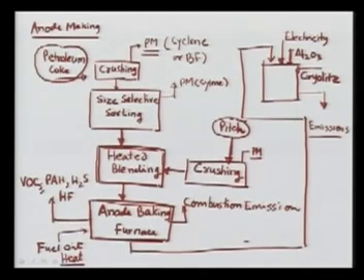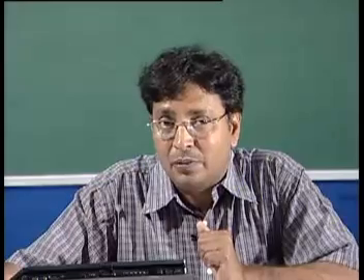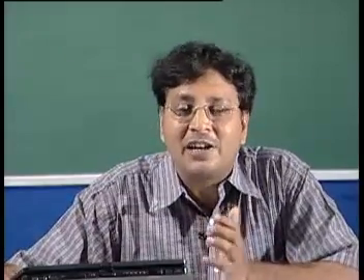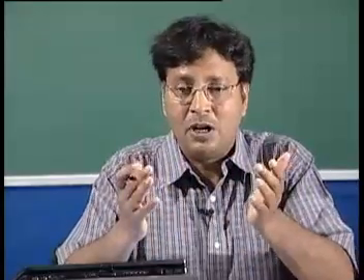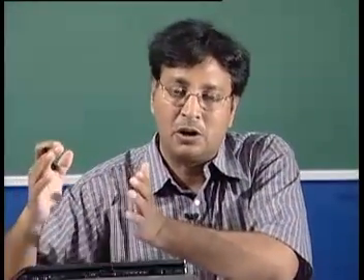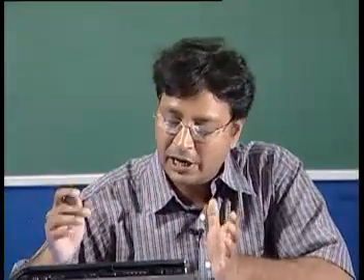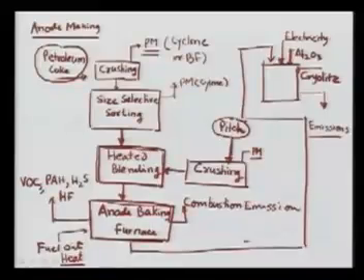But remember that the flue gases from the fuel oil do not come into direct contact with the paste anode. Otherwise the anode will start burning itself. So it is an indirect heating: at one point there is a block of anode, and there is another conduit or pipe which is carrying the heat. So indirectly the anode is heated. Once it is heated, it is baked. Once it is baked, then it is in solid form.